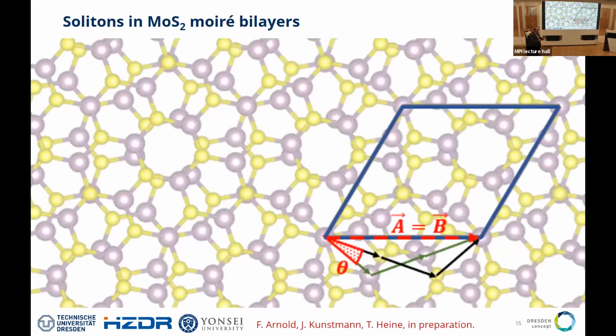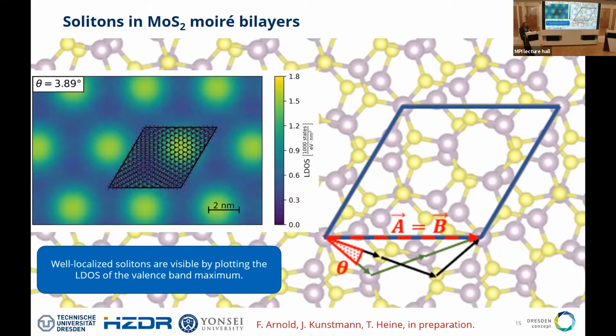So now let me come to solitons. Okay, so now let's get a little bit more physical. So assume we have MoS2. And of course, we all know in MoS2, we have these moiré bilayers. Now I have to play a little bit here because there are some videos included. So what we all know is, right, you can put that at a certain angle, so that here is almost 4 degrees. And then you have the structural picture, and what you see behind are the solitons in a very poor man's representation. We are just plotting the local density of states at the top of the conduction band, of the valence band, I'm sorry. And then you can change the twist angle, right?